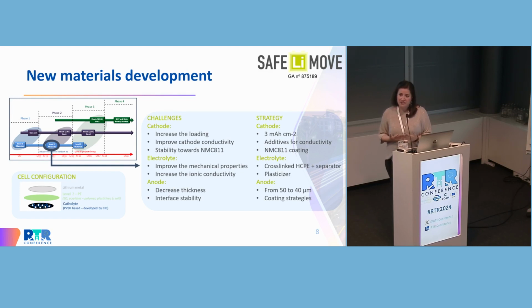And also we needed to increase the ionic conductivity. So we play with different molecular weights of the type of polymers in order to push this property. And then in the case of the anode, there are two different topics. From one side, we wanted to further increase the energy density, so we needed to decrease the thickness of the lithium metal. So we went from 50 to 40 microns. And then also we wanted to improve the interface stability, so we work on coating strategies for the lithium metal.